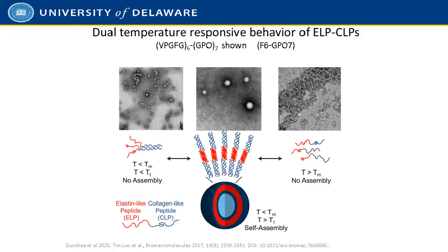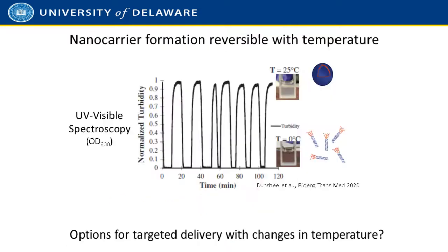It's just like a mess of stuff aggregated on the TEM grid during drying. We know from the light scattering results that those molecules are soluble, and that's because the collagen triple helix unfolds. So instead of having this little mushroom-like structure, we have individually soluble molecules. So that allows us to transition these nanoparticles through different temperatures over repeated numbers of cycles. So you can see in this case, we're traversing through the lower temperature. So we're dissolving the nanoparticles to form the little mushroom-like structures that don't scatter light.